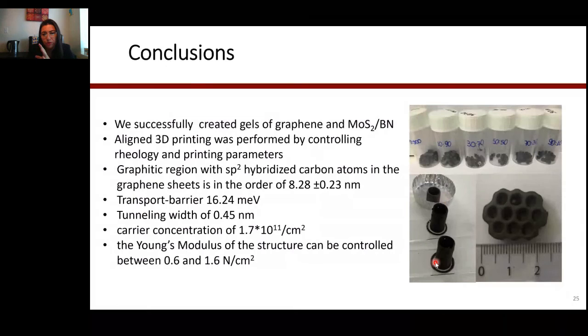We were able to have a graphene structure printed, and there were smaller devices too, such as the electrodes and the hollow cylinders. It was really interesting that we were able to obtain the different concentrations and print with them.